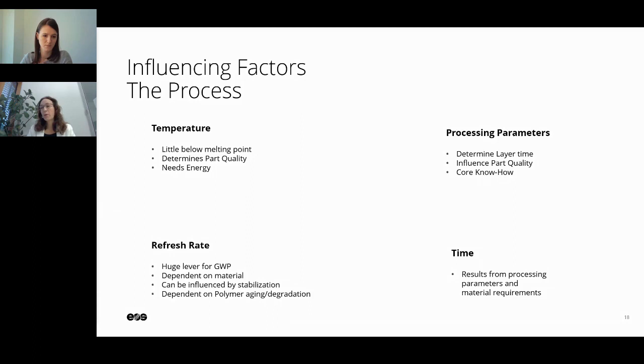material. The more a material ages and changes during that hot process, the lower the refresh rate is, meaning the more new material I have to add in order to have a stable process. This refresh rate can be influenced, for example, by the stabilization of a polymer. So I can really chemically stabilize a material, but that's hard to balance. And it's, as I said, dependent on the polymer aging and degradation.